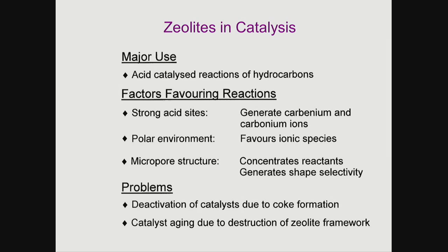They don't last that long in FCC. Do you remember how long they last in fluid catalytic cracking? I told you last week. Anybody remember? 15 milliseconds to half of a second type thing. So that's how quickly they deactivate. And that's the thing with the big hole in the middle that I said was like a pressure cooker. You've got a little hole opening up into this big hole, then the molecule gets in, it reacts on the inside, it oligomerizes and makes lots of other things, and away you go. It's coked up, it's dead.